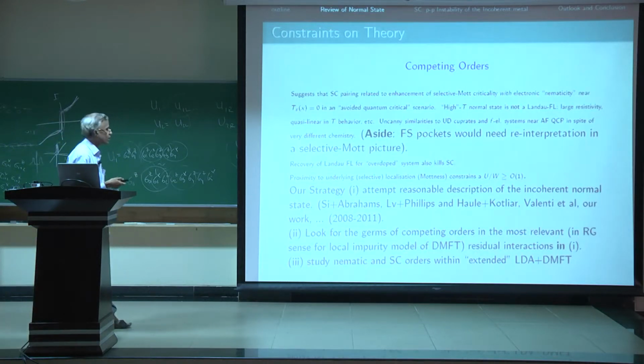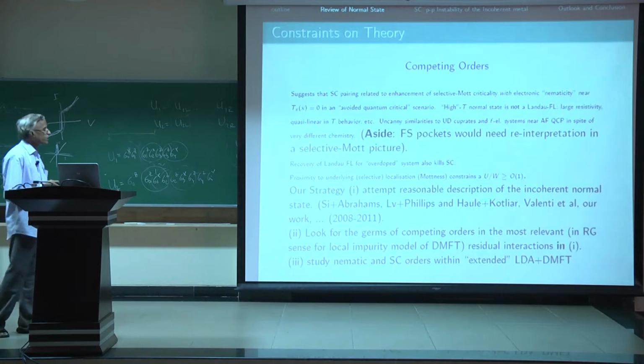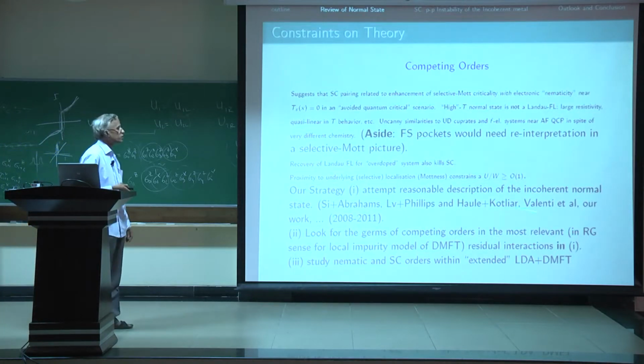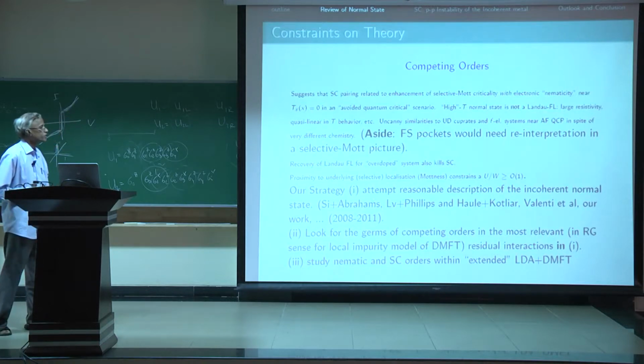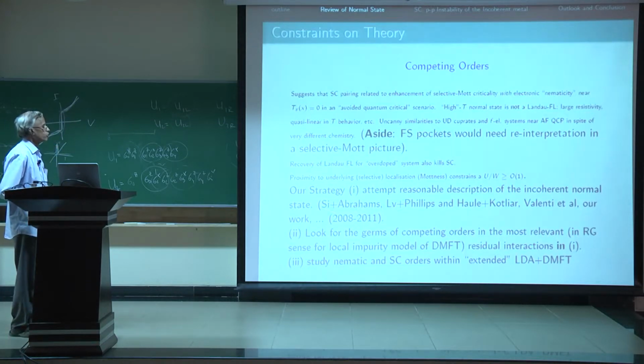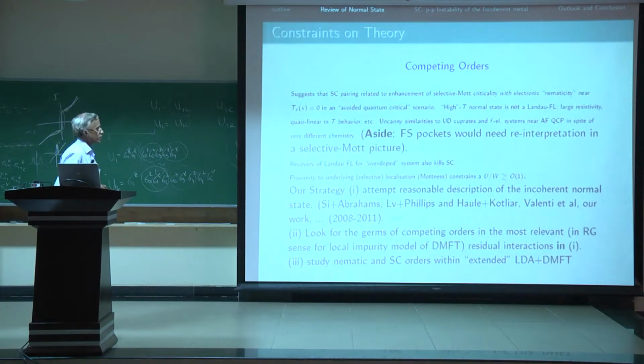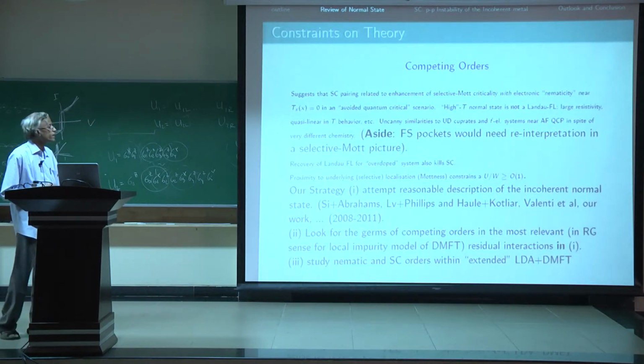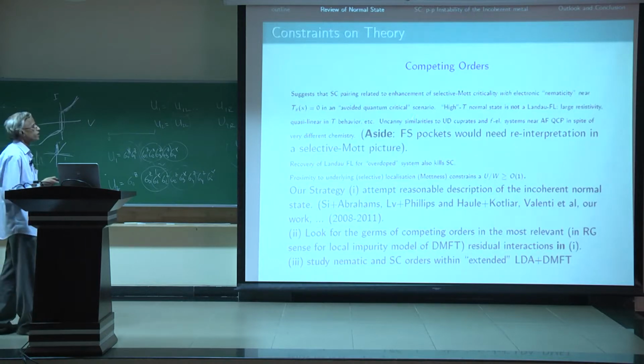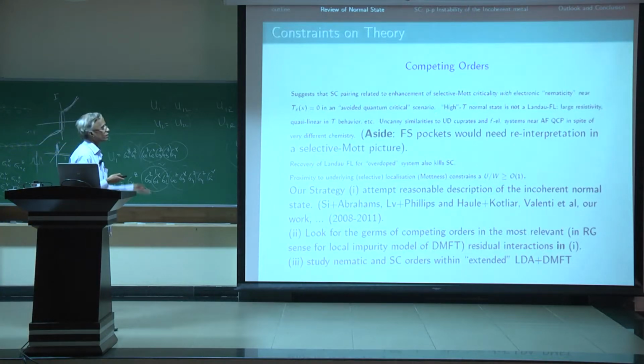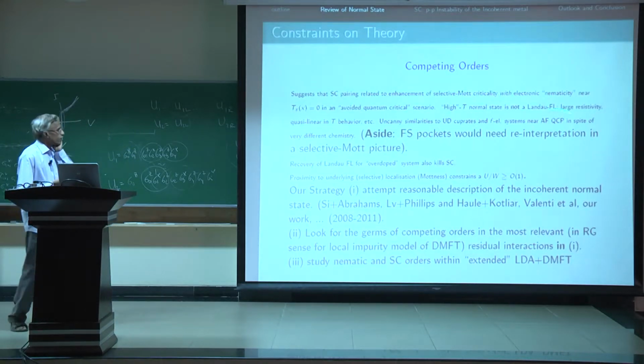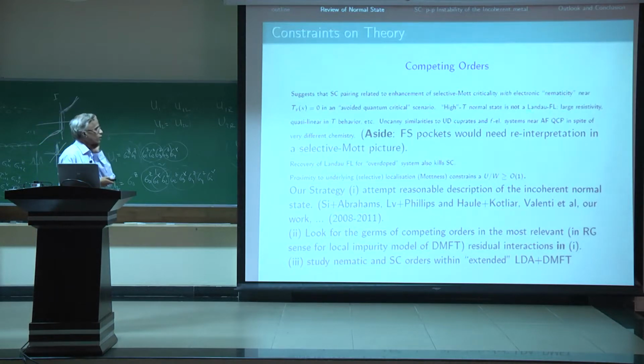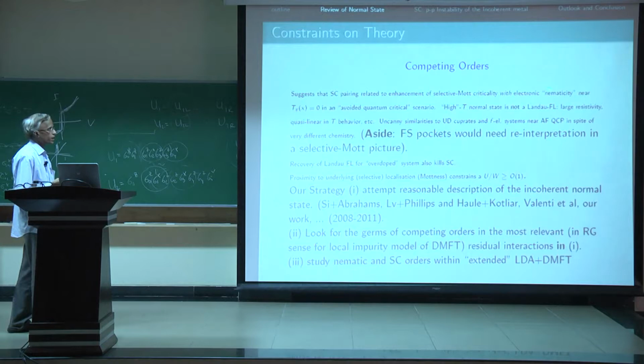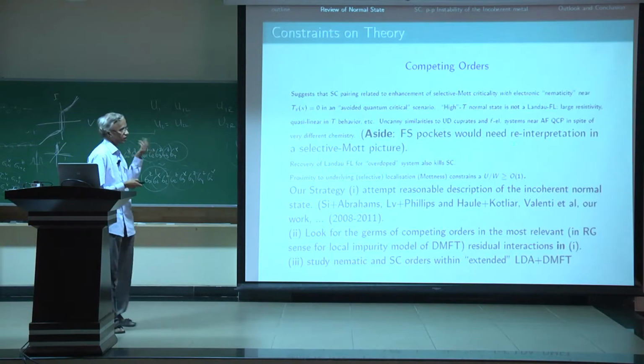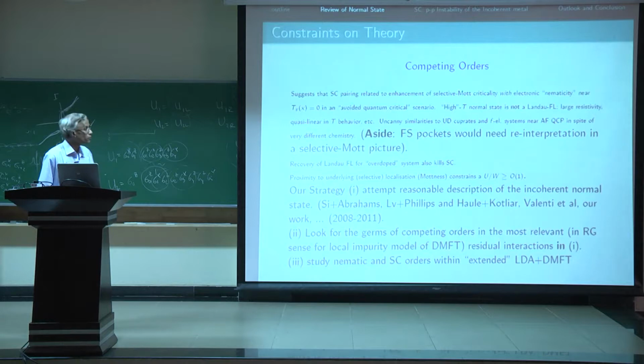Okay. So given all these, our strategy was basically to first attempt a reasonable description of the incoherent normal state itself, and this view has been taken by a lot of groups from the beginning of 2008 itself. There is an alternative view which basically posits that the antiferromagnetism in iron arsenides is dominantly driven by Fermi surface nesting, as one would expect from the band structure calculations for these systems, and that when you dope, the antiferromagnetic instability is basically preempted in favor of superconductivity.